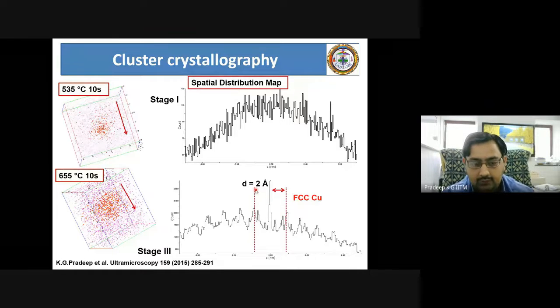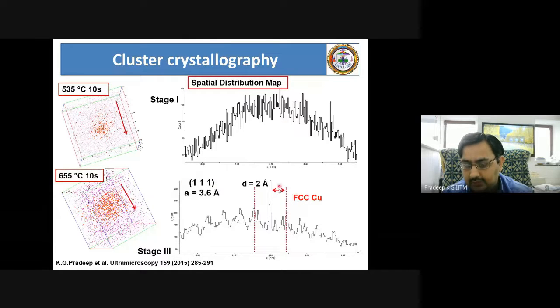Now, if you assume this is going to have a 1-1-1 orientation of an FCC crystal, then you can say the copper cluster is a face-centered cubic copper cluster with a lattice parameter of 3.6 angstrom. That means even in a 5 to 6 nanometer object in a 3-dimensional shape, we are able to get the atomic distribution, precise chemical identification, plus the crystallographic information.